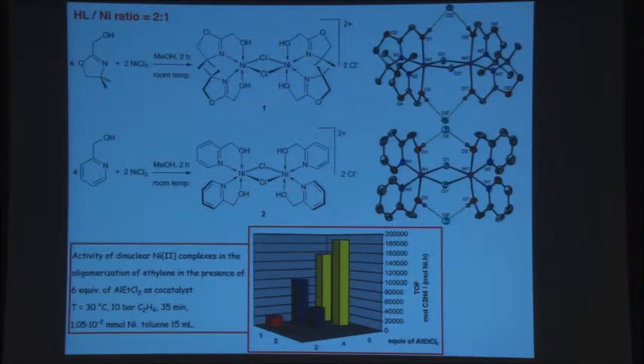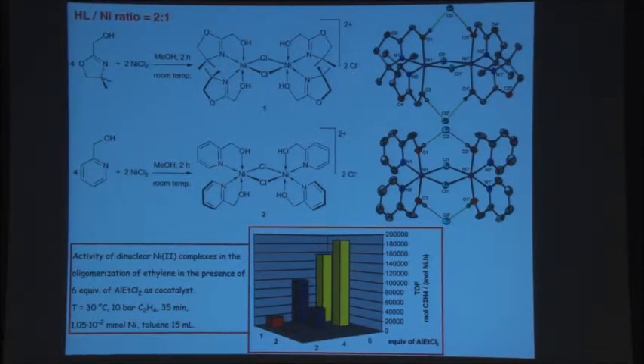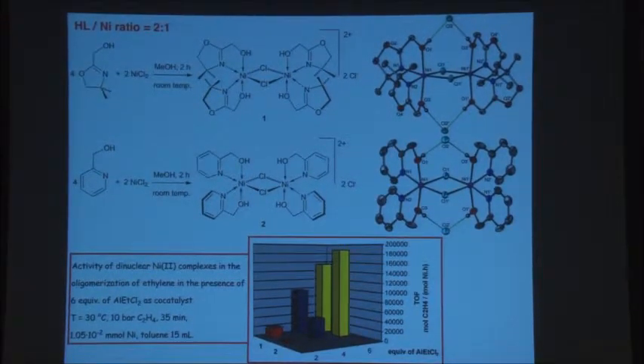Now, X-ray diffraction studies show that actually these chlorides are not miles away from the metal center. They're actually stabilized by hydrogen bonding with the OH group of the alcohol functions. So the two external chlorides, if you wish, not coordinated to the metal, are still not too far away from the metal centers. They are here and there.